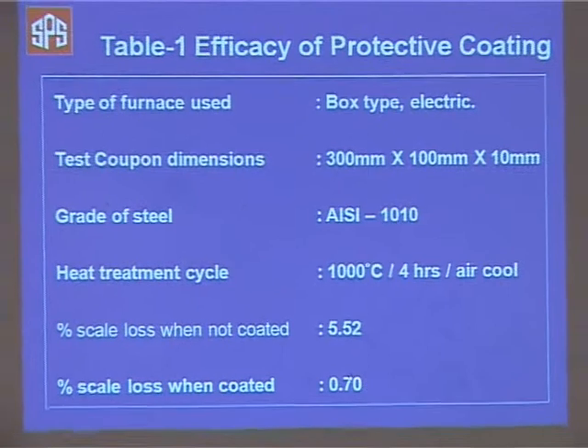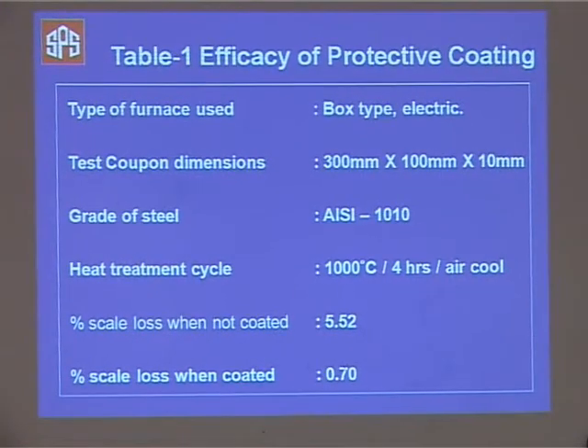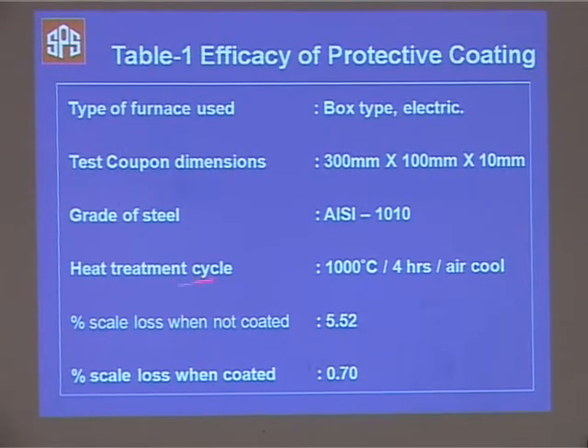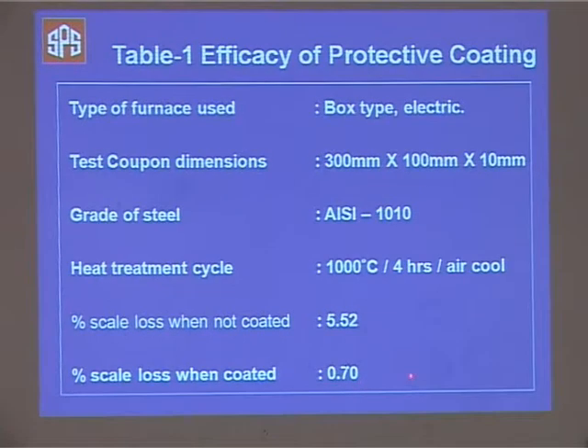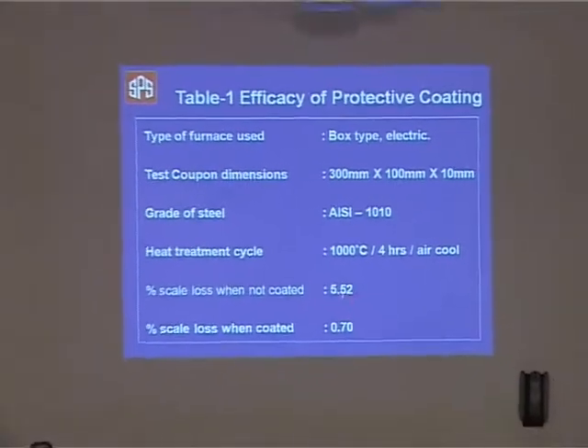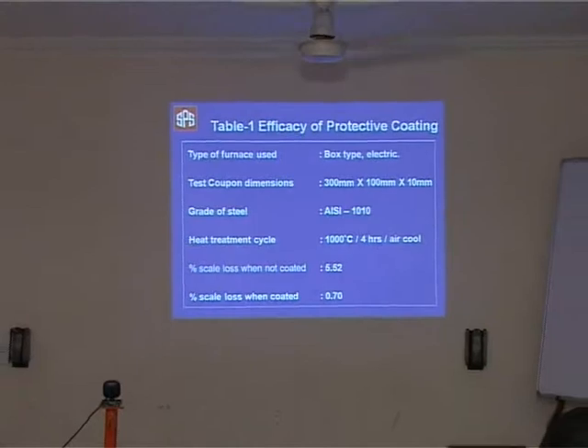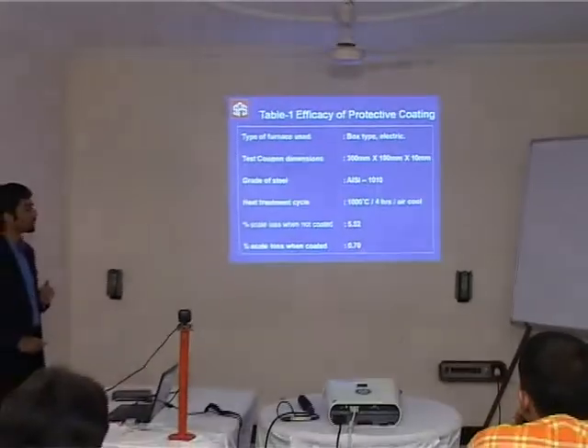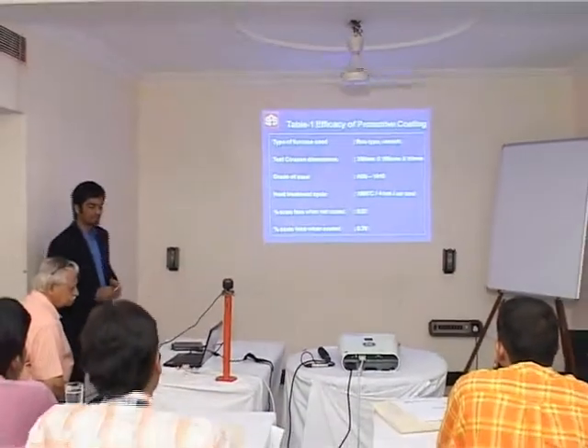This is a tabular representation of the same thing. The furnace used over here is a regular box type electric furnace, and grade of steel AISI 1010. This is your heat treatment cycle, and you can see that the scale loss when coated, we had a saving of approximately 4.82%. When not coated, the scale loss is 5.52%, and it has considerably dropped when we have used an anti-scale compound.